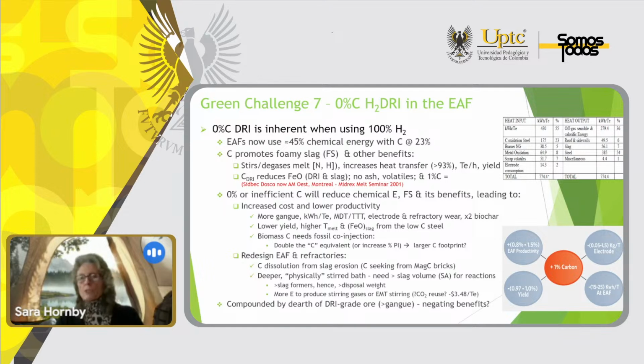It also has none of the ash volatiles associated with carbon that would be injected. The 1% carbon has been shown by ArcelorMittal in Montreal, that used to be Sidbec-Dosco, to give you up to 1.5% increase in productivity, up to 1.5 kilograms per ton reduction in electrode wear, up to 25 kilowatt hours per ton reduction in power requirements, and up to 1% increase in yield.